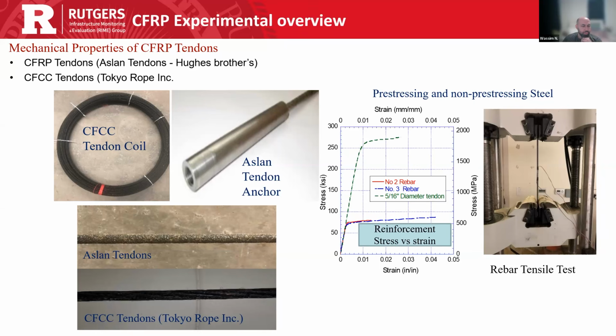The work involves CFRP tendons used as a pre-stressing material for beams. We used two types of CFRP tendons, the CFCC manufactured by Tokyo Rope and the CFRP manufactured by Hughes Brothers. You can see both CFRP tendon types. One of them is more flexible and it comes in coils. The other one resembles an FRP bar, but they both have very similar properties: an ultimate strain of 1.7% and an ultimate stress of 320 up to 400 KSI, which is much higher than that of the steel, which is around 270 for the tendon and around 80 for the bars.